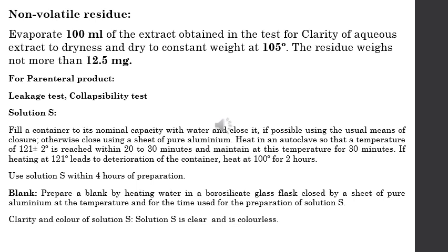If heating at 121 leads to deterioration, heat the container at 100 degrees Celsius for 2 hours. Now this solution is used within 4 hours of preparation. Similarly, we have to prepare a blank and then test for clarity and color of the solution. Solution S should be clear and colorless.